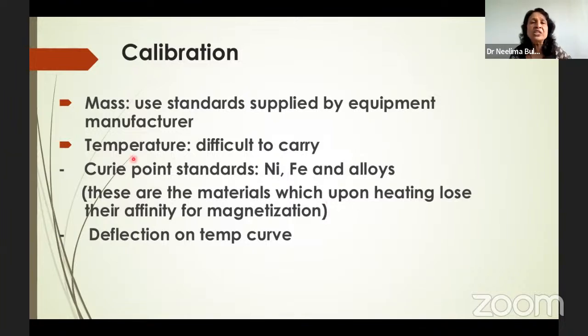So calibration of TGA includes mass calibration. Always use the standards supplied by the equipment manufacturer. And the second thing is temperature calibration, because you are going to measure the thermal stability of the sample. So temperature calibration is extremely important. It is a little bit difficult to carry out, but nowadays manufacturers provide us the Curie point standards.